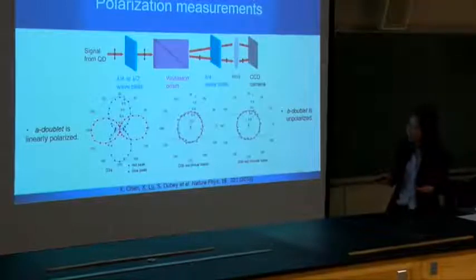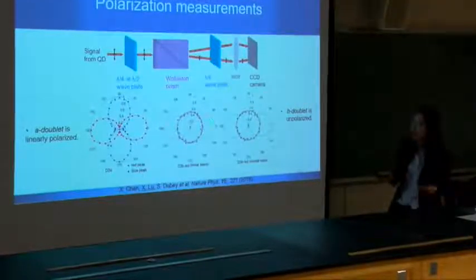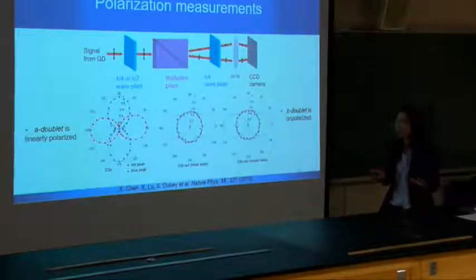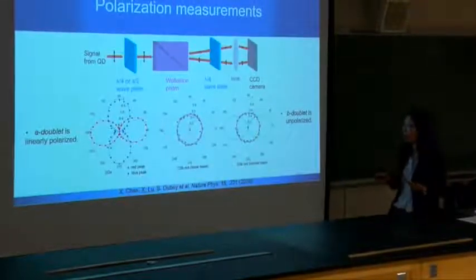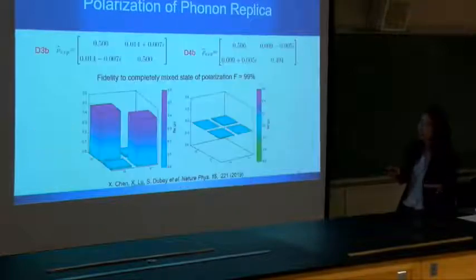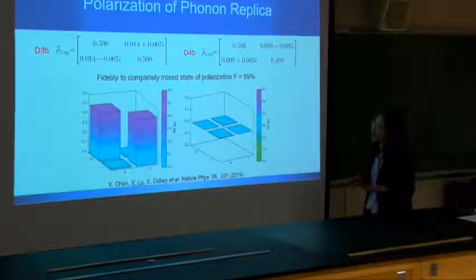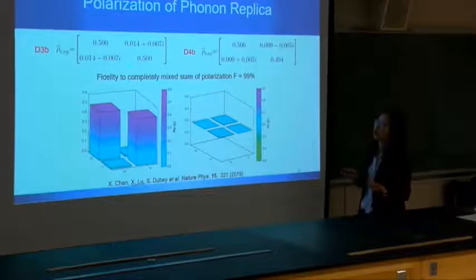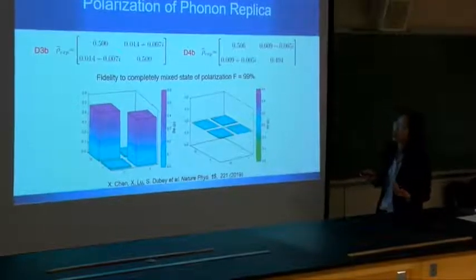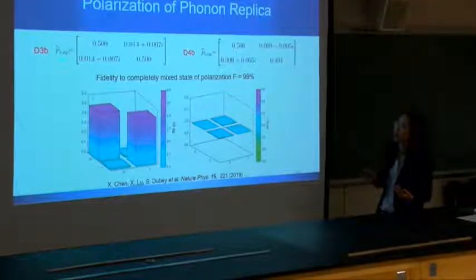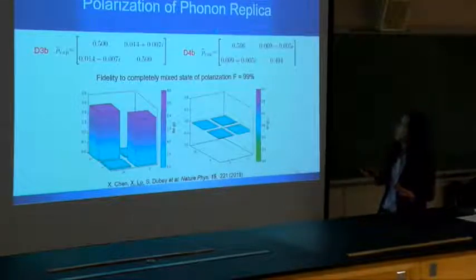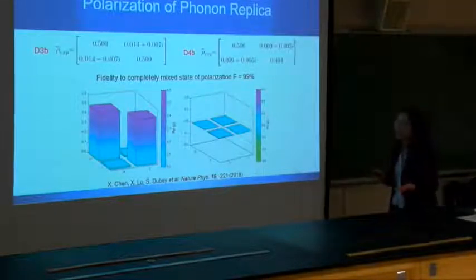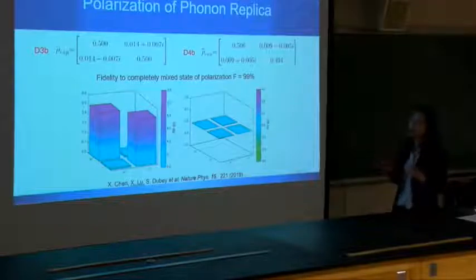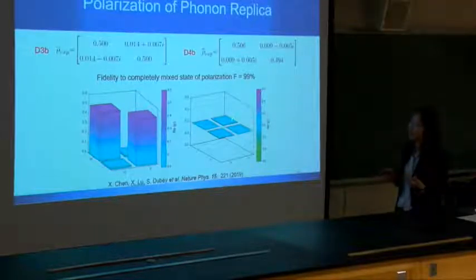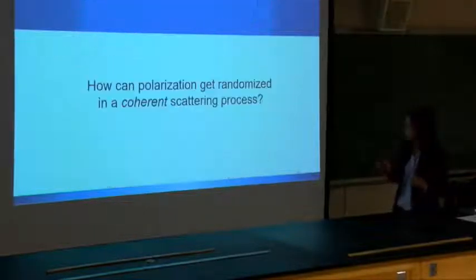No matter in linear basis or circular basis, it doesn't depend on the measurement collection angle. Which means that it is unpolarized. But that's kind of weird. And from the polarization measurement, we extract the Stokes parameters and construct the density matrix for the phonon replica. We compare it to a mixed state and found that the phonon replica is very close to a mixed state with fidelity of 99%.